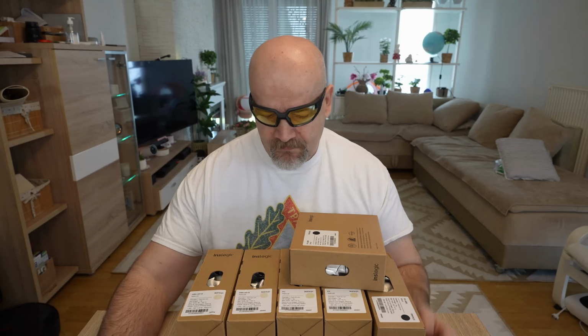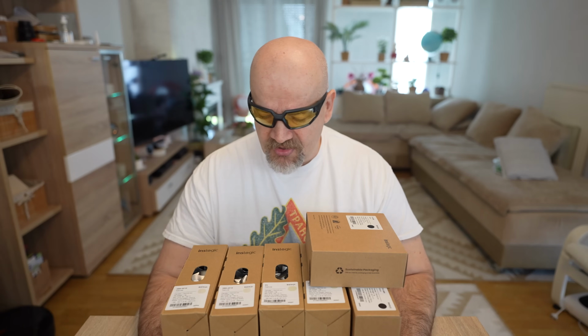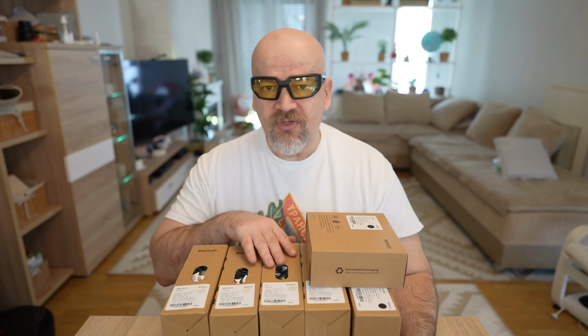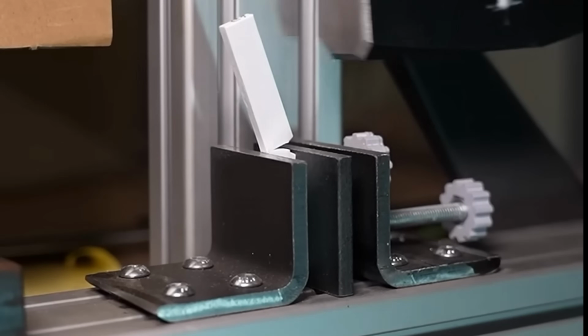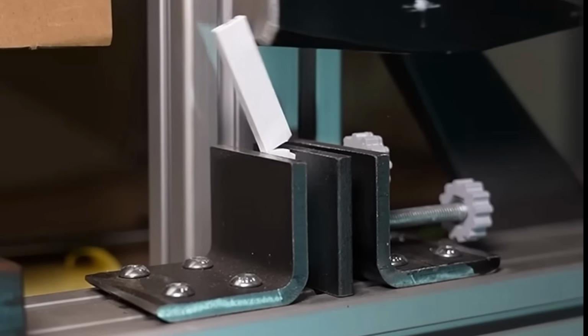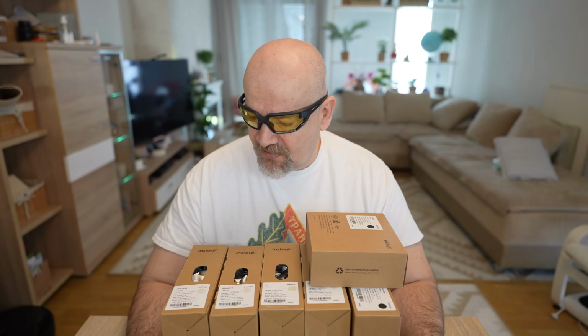For some overall thoughts, and later we check the website for some additional information: these technical filaments should be very tough. Except the PC, I'm not sure here, because I tested polycarbonate filaments which are very brittle and also very tough, depending on the additives. But every PC-ABS filament I tested so far is an extremely tough material, and sometimes it didn't even break under the half kilogram hammer on my DIY impact tester.